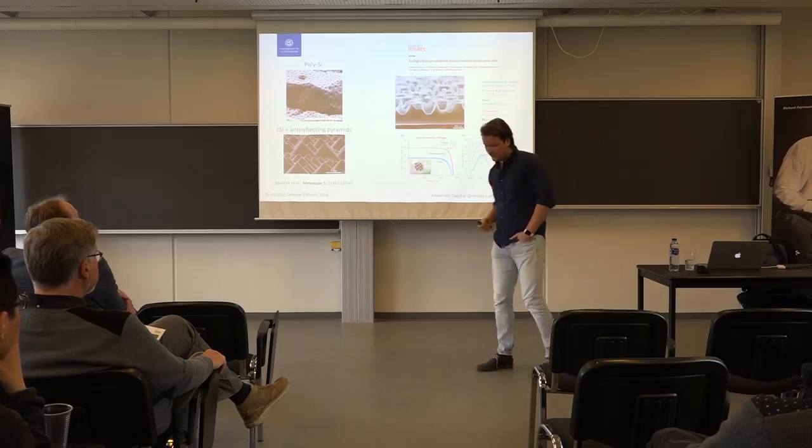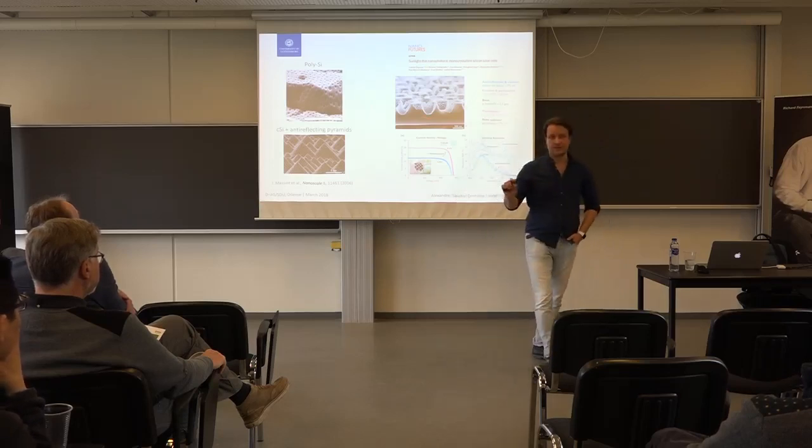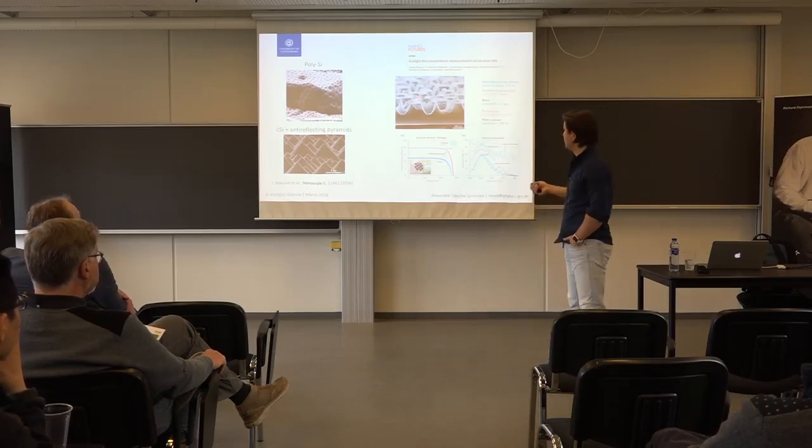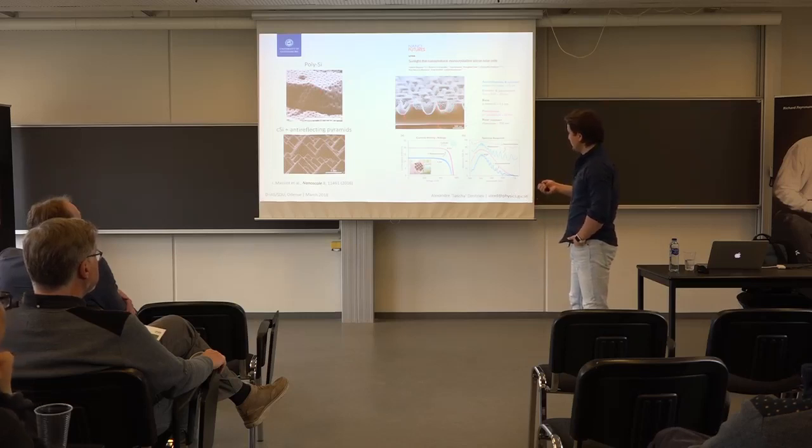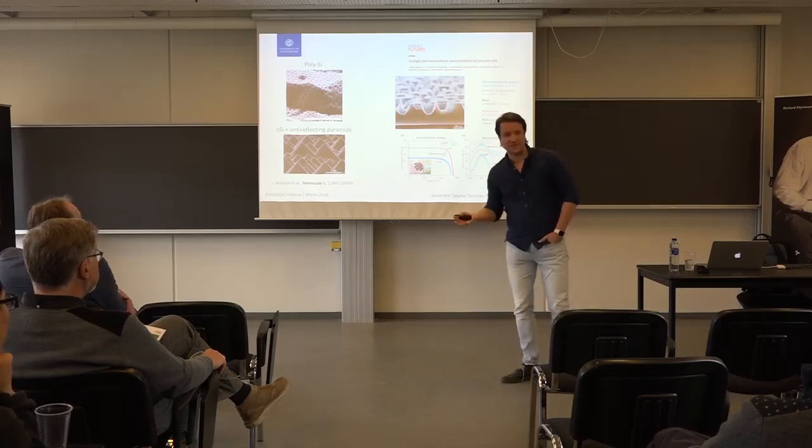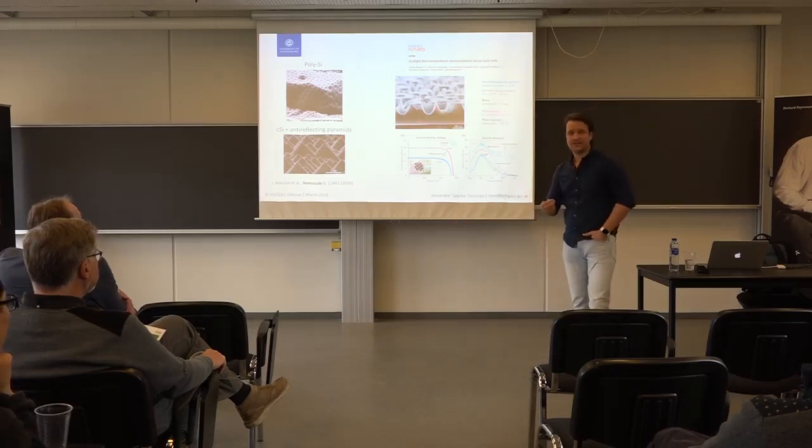So you actually have semi-transparent crystalline solar cells, and just because we patterned them with these little holes on top, it looks something like that. And we etch the solar cell. This is the thickness of the original solar cell. We essentially remove 50% of that material, and yet it is a reasonably high efficiency cell.